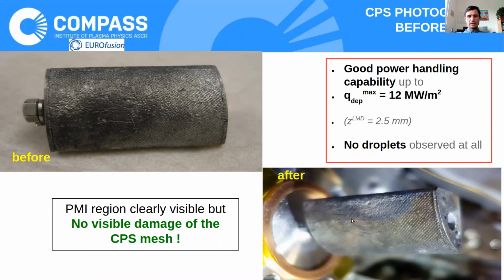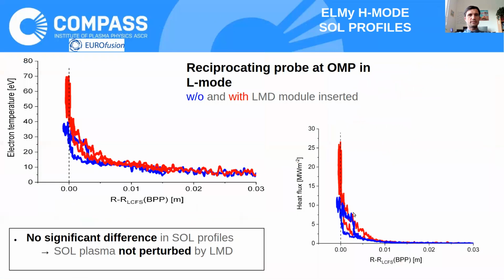You can see the area which was exposed to plasma. It changed the color. Otherwise, there is no visible damage of the capillary pore structure mesh. And we also observed no droplets expelled from the surface.